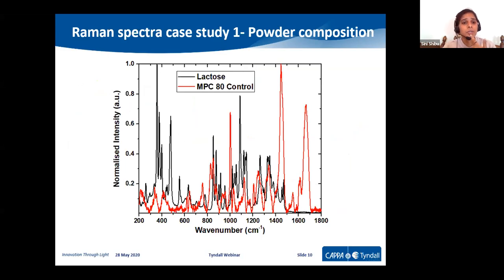So that's how I'm showing this Raman spectra of lactose and MPC 80 control. This is MPC, milk protein concentrate 80. That means 80% casein powders. The lactose peak is in the background. So it is very evident from this graph that the peaks around 1446 and the peaks around 1640 and 50 are only from the milk proteins. It is not because of the lactose. So it is mainly because of the casein, the presence of casein is showing in this graph.